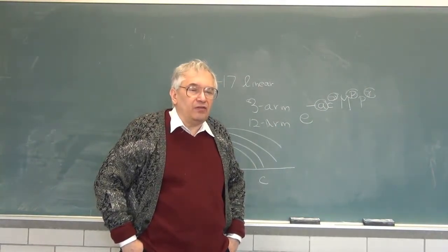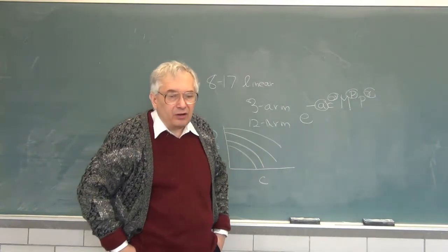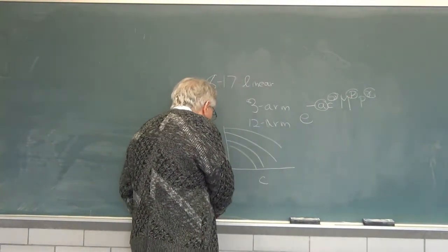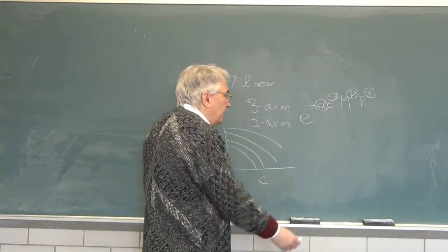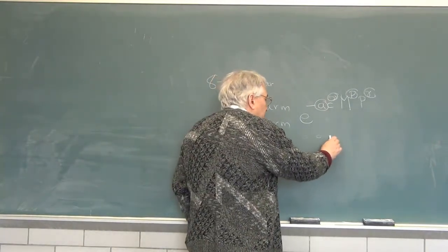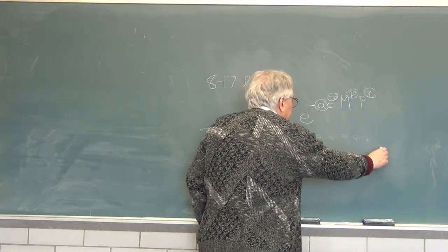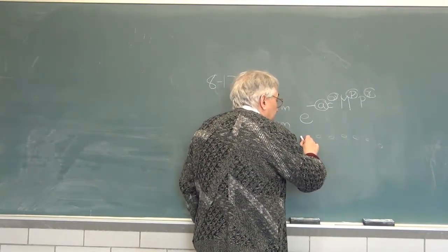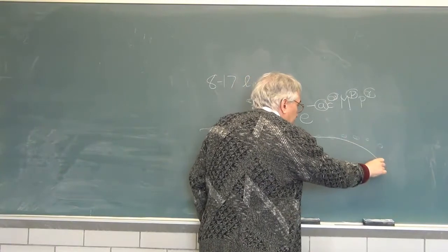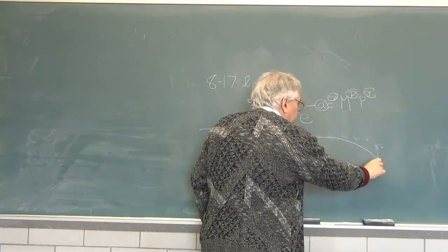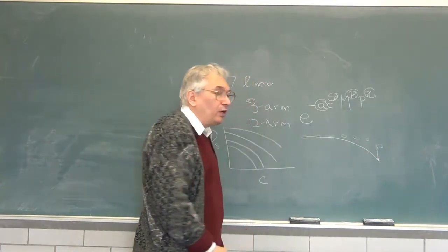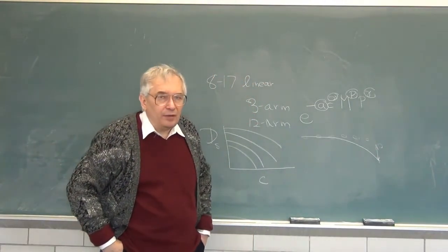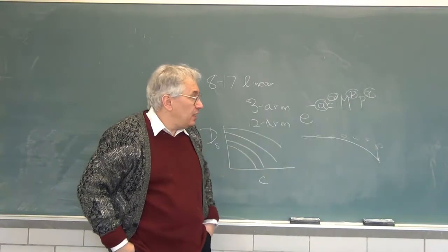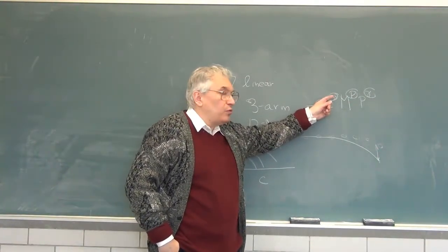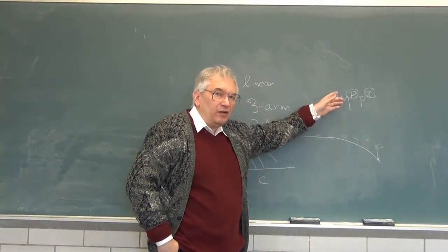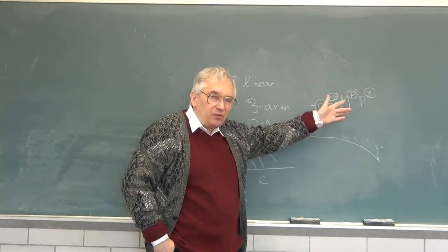There is one point, if you look hard, where clearly things aren't nearly as good. Namely, if you look at the smallest molecular weight probes, the measurements do this. The fitted curve does that, and there is quite visible discrepancy. You might ask, gee, what's going on? Well, what is going on, if you compare with the single fits, is that the concentration exponent depends on the molecular weight of the probe and the matrix in some combination.